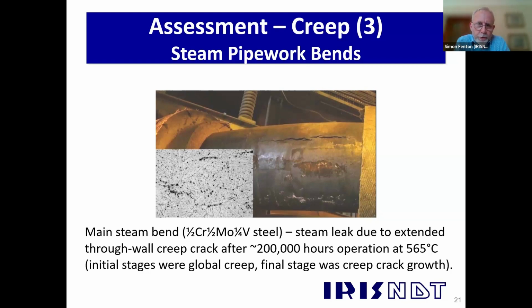But at the time, we were monitoring 1 or 2 bends on that power station, each outage every 4 years with replicas and NDT. And the discovery of this in 2006 led to a massive escalation in the amount of replicas we were putting onto parent material. We were already looking at lots of butt welds, because they were known to suffer damage earlier in life. But the parent material, until this stage, had not really given us any problems. So there was suddenly an overnight need to train up new replicators. And again, it became replica on an industrial scale, really, to monitor this damage.